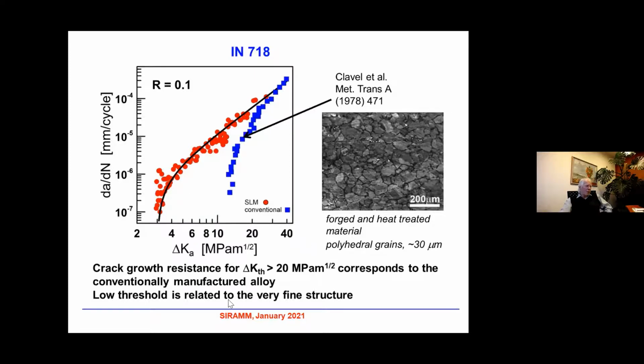So I can conclude that crack growth resistance for delta K above 20 megapascal meter to 1/2 corresponds to the conventionally manufactured alloy, and the low threshold is related to the very fine microstructure, and the material behavior is much worse.